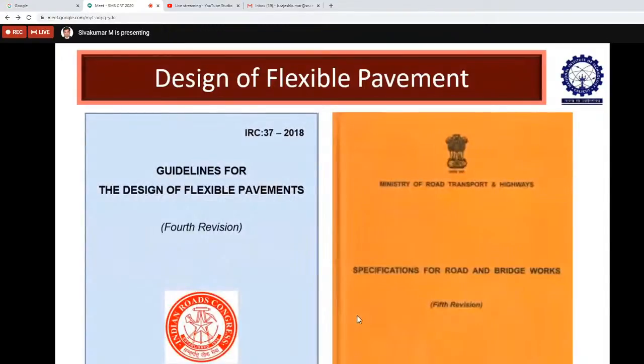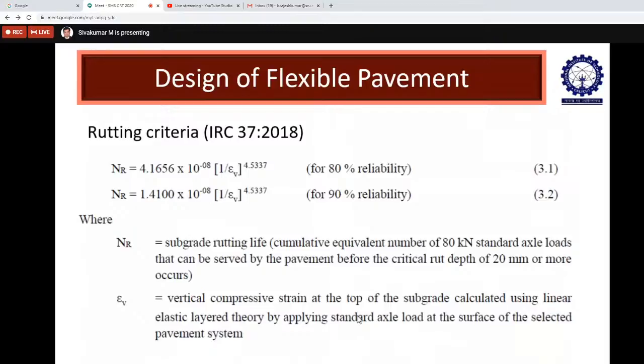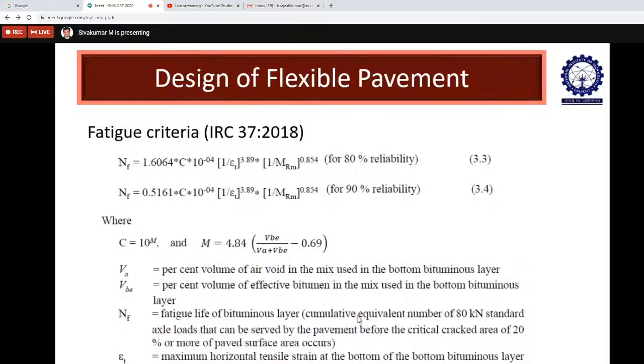So these are the two references I have taken for the design of flexible pavements: for design guidelines, IRC 37 2018, and for the standards of materials or the thicknesses, more specifications. As we discussed in the previous slides, rutting criteria is a major one where the mechanical response is observed. So the models consider both 80% reliability as well as 90% reliability in IRC 37, and also the fatigue criteria, where the mix volumetric property, in terms of volume of air voids and volume of effective bitumen, is also considered, since the volumetric property contributes to the fatigue failure of the pavement. So both criteria are considered with the mechanical response.